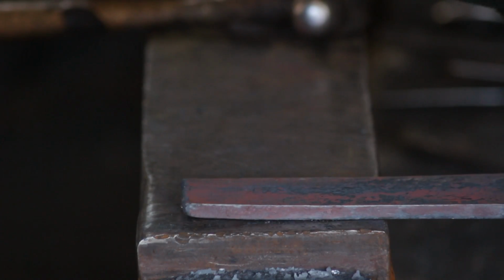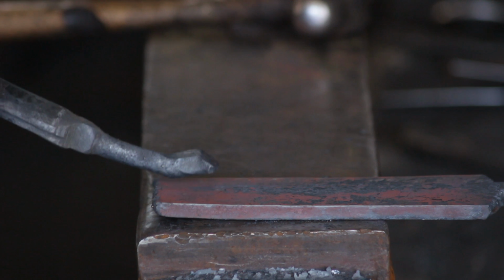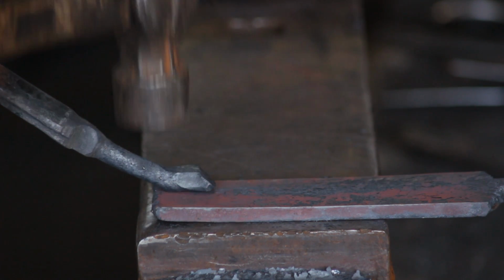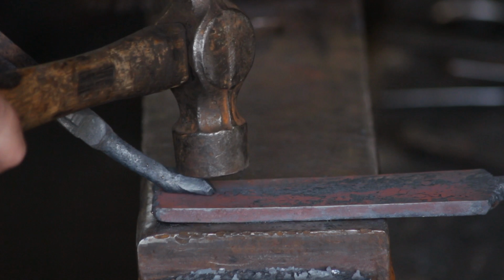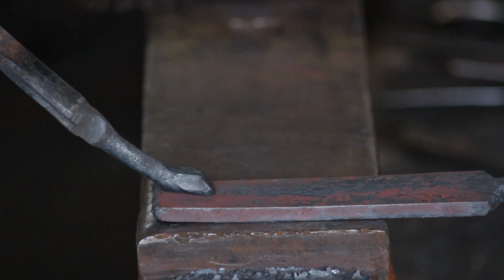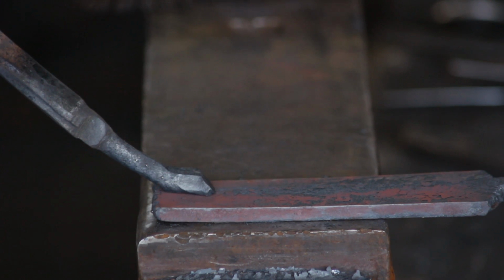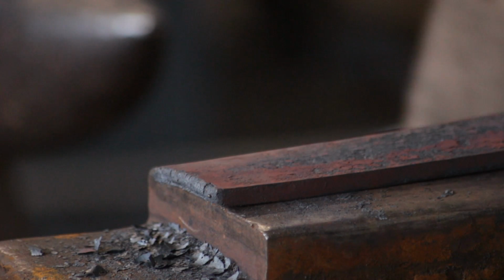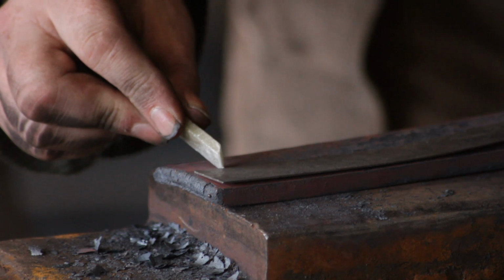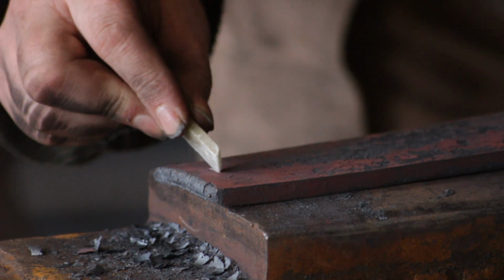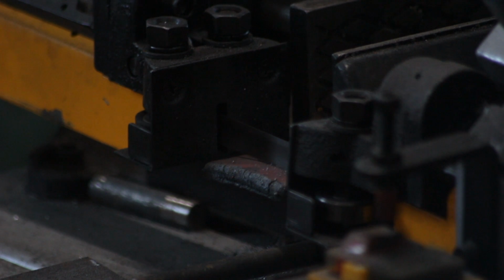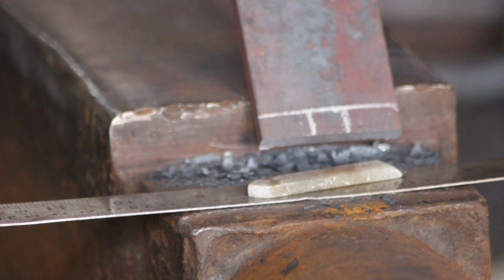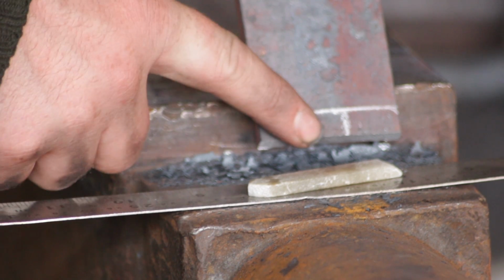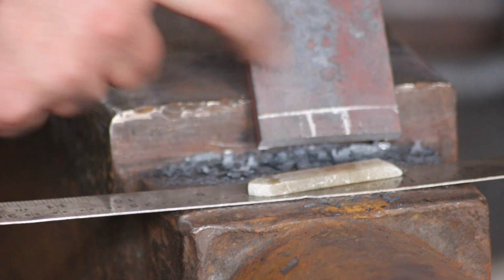So this is how the blade will be welded to this. Now, if you look at the transition between the tang and the scarf, you will see that I have a shear plane here. So what I will do is I will just take 15mm off the end of the wrought iron billet, and that is just purely arbitrary. I just want to get that mankiness off the end where it hasn't quite welded and where it's a bit mucky. And I will actually cut out a 10mm tab from the centre of the billet.